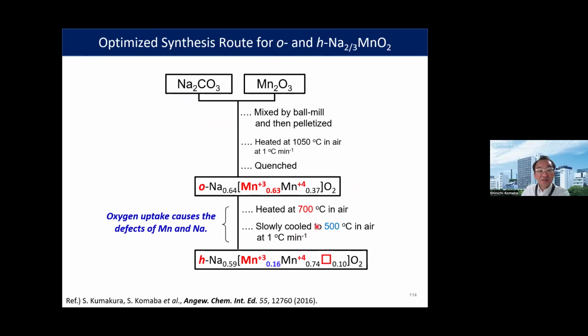The point is here. In the case of 1050 degrees Celsius, we have a quite nice orthorhombic distorted structure. But after this post-heat treatment, through additional low temperature heat treatment, because of oxygen uptake, it causes defects at the manganese and sodium sites, and then we have 10% vacancy on the manganese site. Then there is less trivalent manganese, and this manganese cooperative distortion disappears for this layered oxide.